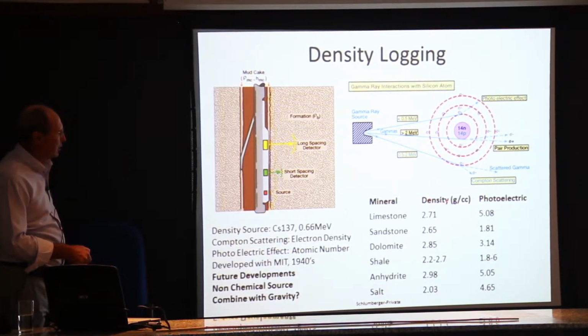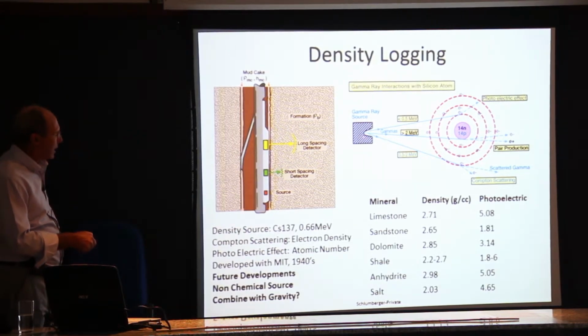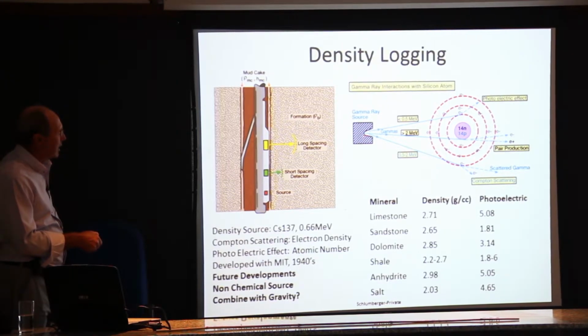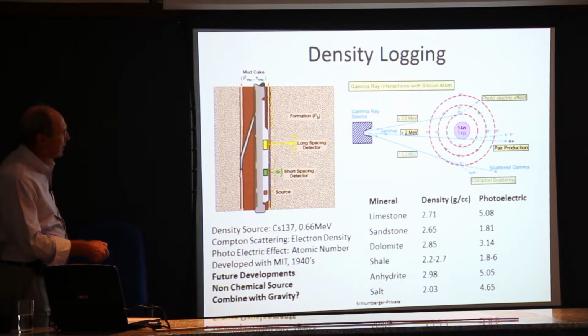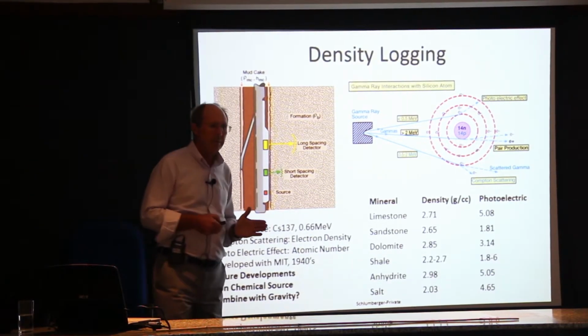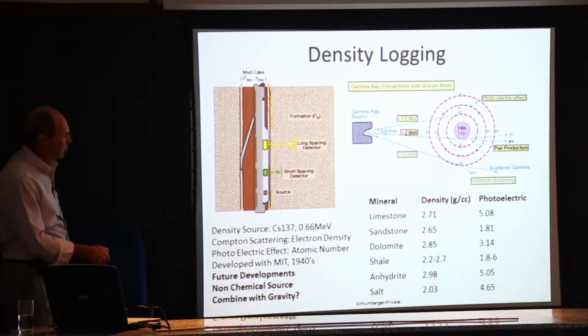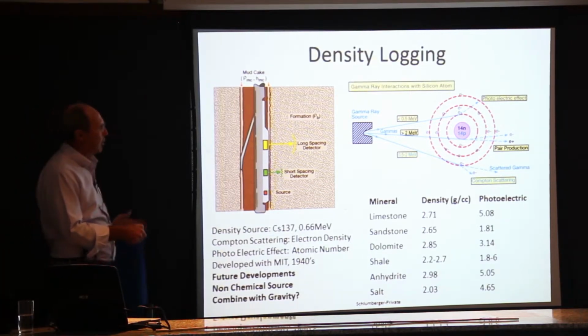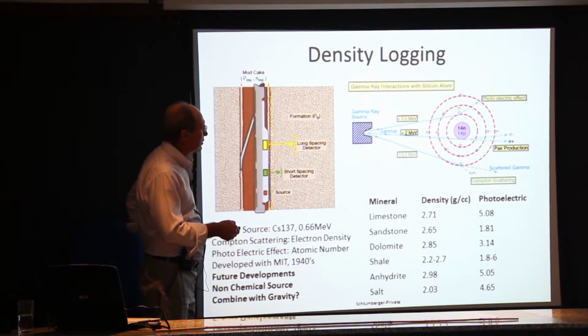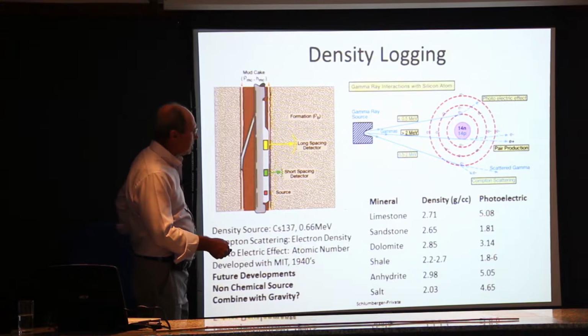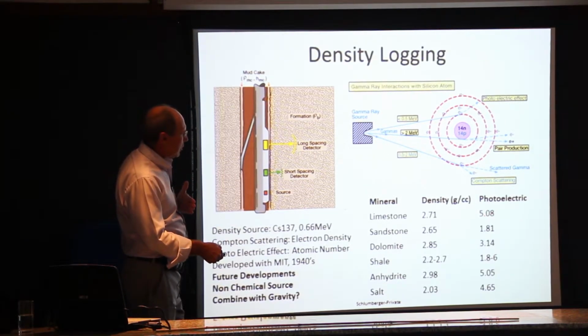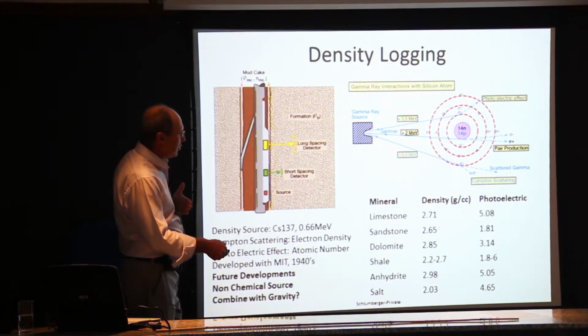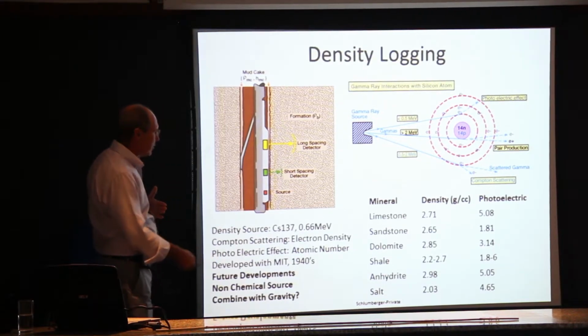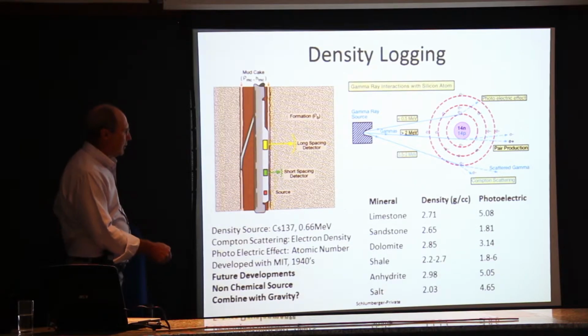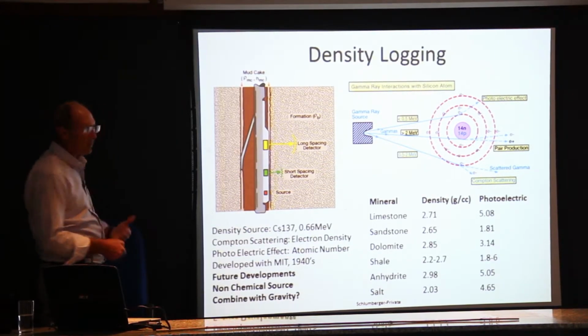Now we have a second measurement with the density log based on the photoelectric effect, which is a different mechanism. So with the density log, we emit high energy gamma rays, and there are two types of interaction. One is called Compton scattering, which is sensitive to the electron density of the minerals, and the electron density is directly proportional to the bulk density of the formation. And then we have the photoelectric effect, which is a lower energy interaction. And the photoelectric effect tells us the photoelectric cross-section of the formation, which is another indication of the mineralogy. So using this, we can get a better understanding of how much limestone, sandstone, and dolomite we have, and then we can actually determine the porosity better because we can determine what the effective bulk density is of the formation.